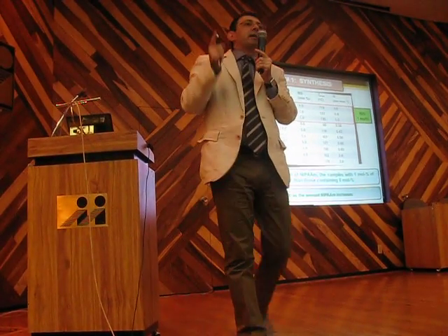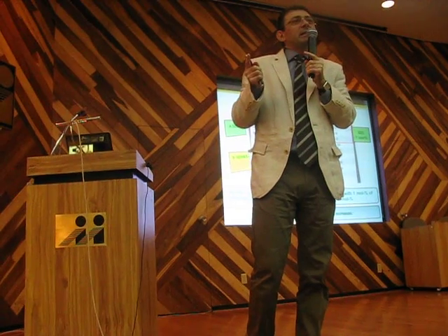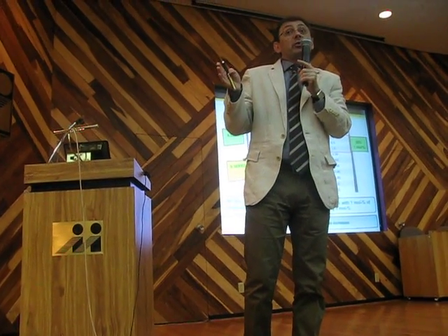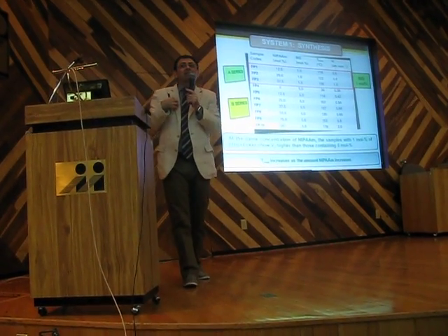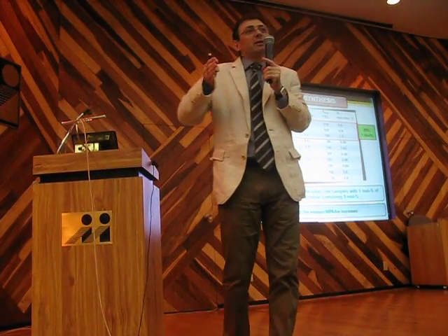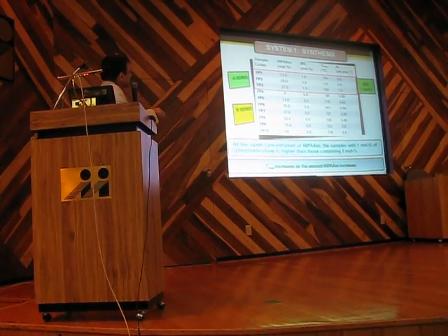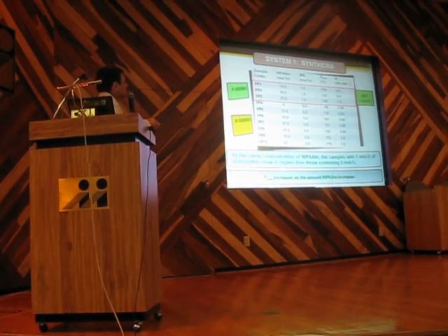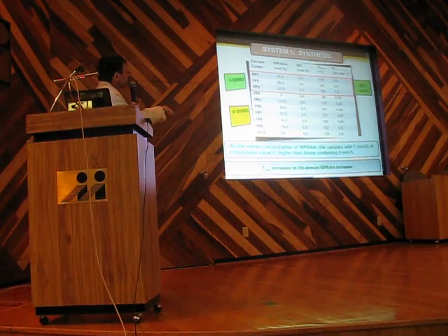Because in that range, frontal polymerization occurred. Because frontal polymerization occurs only in certain ranges. And our job is to find these ranges and possibly to extend them. And we extended the ranges from 0 to 100% by increasing the amount of crosslinker from 1 to 5%.